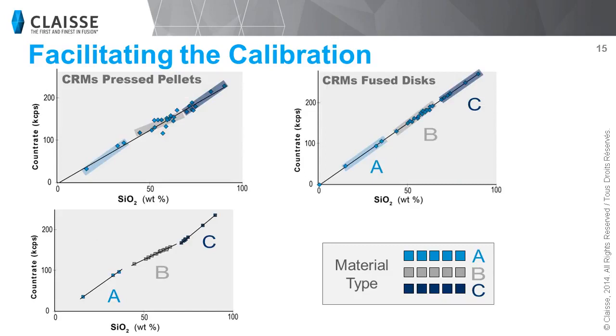You can see here calibrations made by pressed pellets and by fusion for three different production sample types, which are A, B, and C. We see that with pressed pellet, you will need three different calibration curves in order to fit without the mineralogical effect for the three different types of samples, which contains the same component, here silicon dioxide. With fusion, a single calibration curve is needed, thus reducing time to calibrate and lowering the costs.